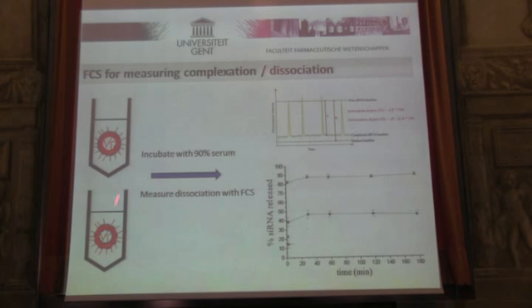So we did these measurements. So those are the two formulations. We incubate with 90% serum. We measure by FCS, as I just have explained. And indeed, compatible with our hypothesis, in this case, we saw 90% release of the siRNA in serum, because this is actually just sitting outside, while in this case we saw 50% release. 50% is still a lot, but at least you keep something inside.